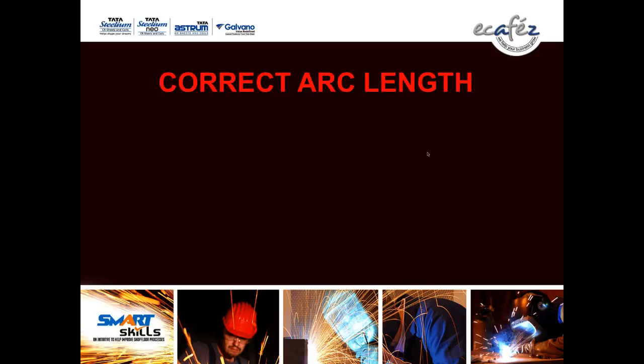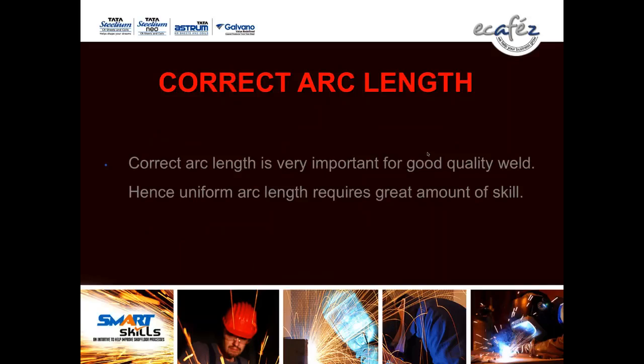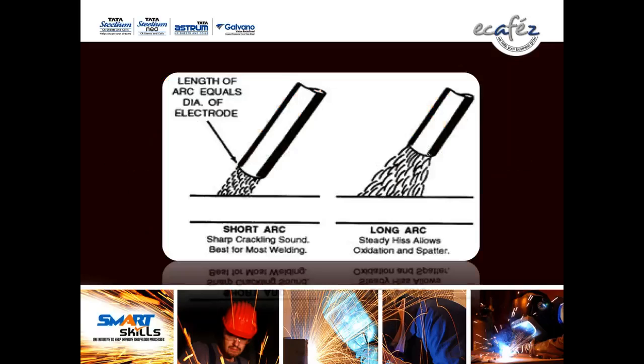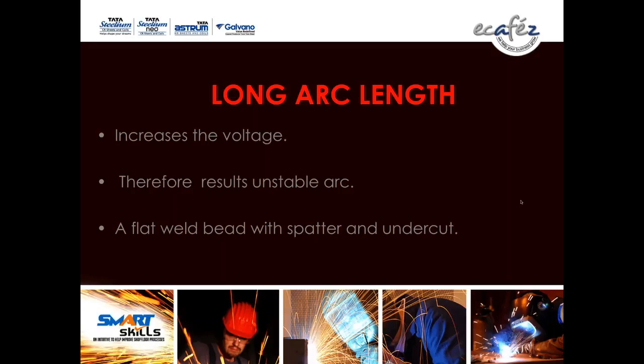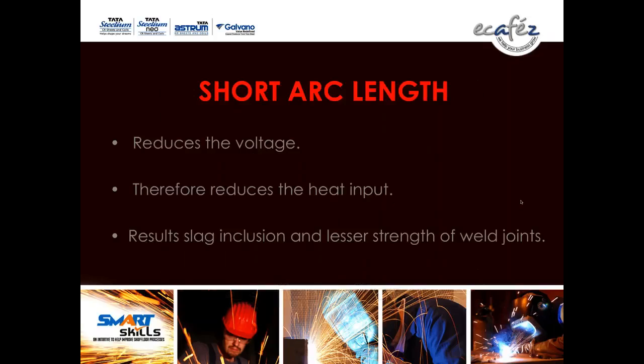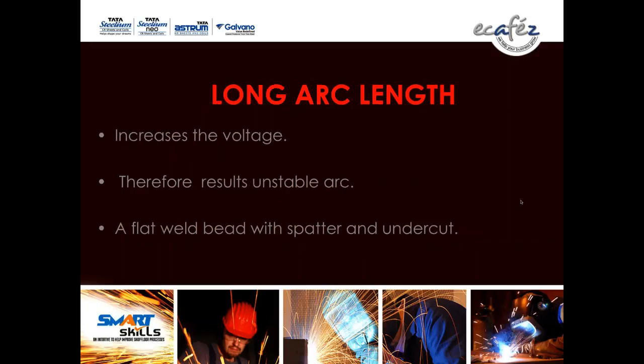Correct arc length is very important for good quality welding. Uniform arc length requires a great amount of skill. See the correct arc length, short arc, long arc. The arc length should be ideal. Short arc length reduces the voltage, therefore reduces the heat input, and results in slag inclusion and lesser strength of the weld joint. Long arc length increases the voltage, therefore results in an unstable arc, a flat weld bead with spatter and undercut.